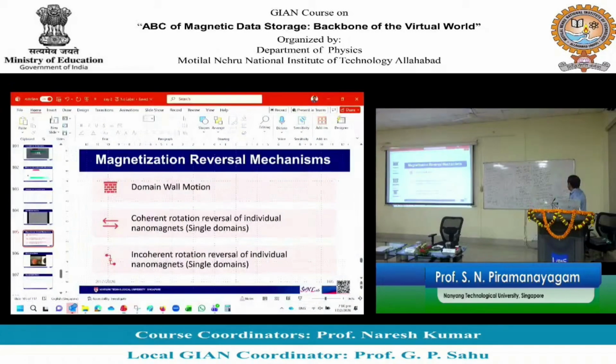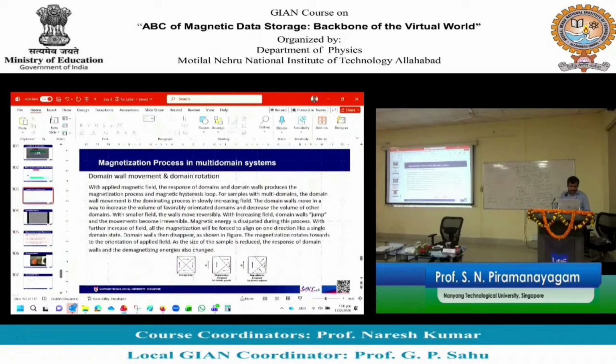However, if you try to reduce magnetostatic energy, but in that process you need to spend more energy for the domain wall, then the domains will not form. That is like losing 1000 rupees to gain 100 rupees; you will not do that, right. So, which one is larger? Ultimately, which one leads to a reduction of overall energy will determine whether the system will form domains or not.